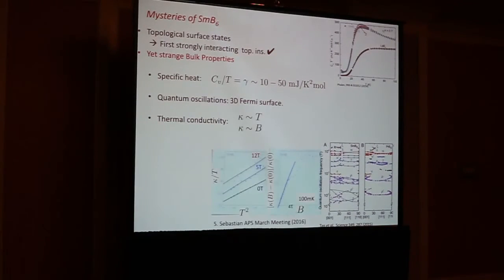The thermal conductivity is also weird, and here I can show you unpublished data which is taken from a camera shot I took at the March meeting from Suchitra Sebastian's work, showing the thermal conductivity, which is proportional to the field at low temperatures. This is truly remarkable. Here's the field dependence at 100 millikelvin. What kind of state of matter gives you a linear in B thermal conductivity? It reminds you of a flux lattice.